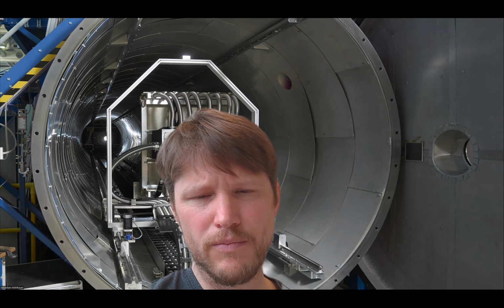Now the reason is that we wanted to include weights depending on the areas where we expect the vortex lattice reflection. Because if we use the conventional way of measuring reflections, we give the same importance to all the areas. So this analysis specifically chooses where we expect the vortex lattice line to appear. And also by using this Bayesian analysis, we can blind those areas that are not of interest. So then we will just see the signal that is coming from the vortex lattice.